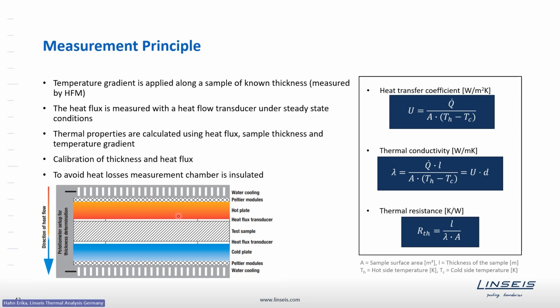The heat flow we measure directly using so-called heat flux transducers, and this signal gives the information we need to find out the thermal conductivity. We also determine the so-called U factor, which is the heat transfer coefficient, which is often used for building materials, being able to group the different building materials and compare them. Also, the thermal resistance of the material is determined using the heat flow meter. The difference compared to the TIM tester is, on the one hand, the size of the sample and the thermal conductivity range, and here within the heat flow meter, as we use the heat flux transducers, we need to calibrate this reading with a reference material.